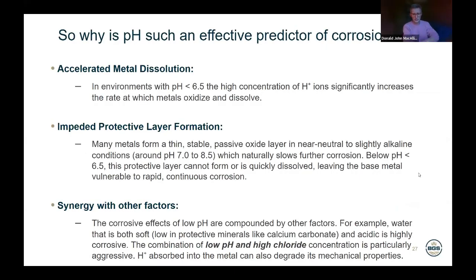So what are the processes that are going on? Why is pH 6.5 such an effective indicator? I'm not going to go into detail on these slides, but there are three main factors. One is that when pH is less than 6.5, the higher concentration of H+ ions in solution accelerates the rate of metal dissolution. Then, when pH is low, it impedes protective layer formation. When you have high concentrations of calcium carbonate in water, for example, you can get a protective layer that forms in the pipes. But when pH is low, that doesn't happen so much, and it slows down that process and also eats up that layer more quickly.